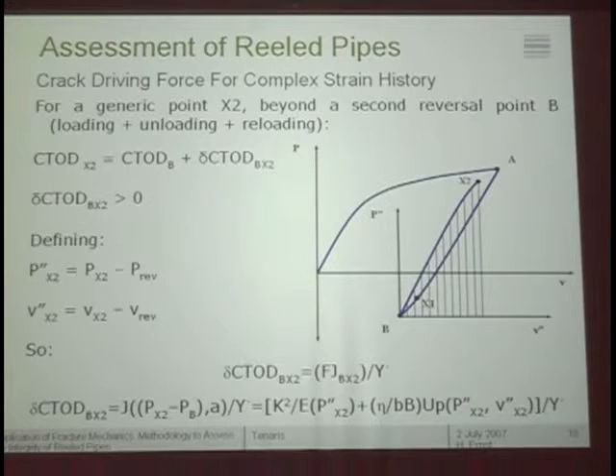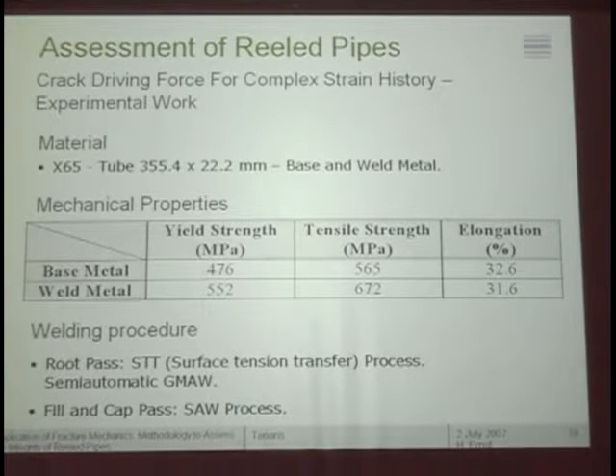So with this very simple model, we thought that we were in a position to predict this evolution of the CTOD to a practical extent, of course. And in order to prove if we were right or close to, or right enough, say, for this purpose, we did some experimental work just to determine the evolution of the crack driving force, no crack growth so far, under complex plastic history. We took a particular material that is one of the ones that we use for this operation.